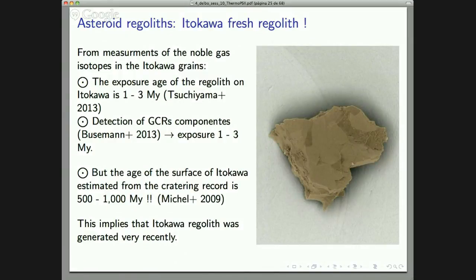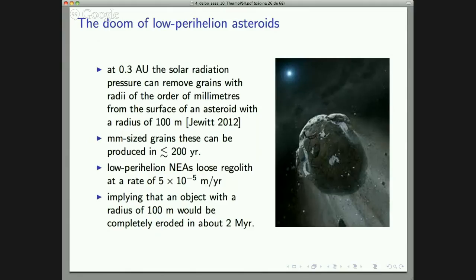The thermal cracking is a strong function of the temperature excursion. So if you are an asteroid that is very close to the sun, you crack like crazy. And for example, if we extrapolate our model to an object 0.3 AU from the sun, we basically produce grains very quickly, almost done. And we can say that the radiation pressure can blow these grains away if the object is small enough, as shown by the calculation of Jewitt.